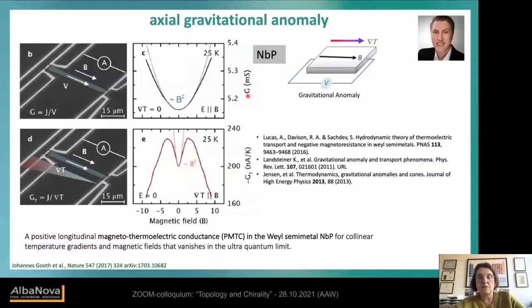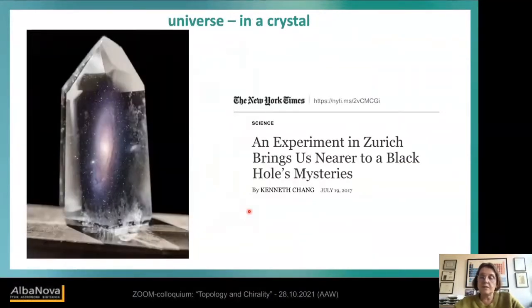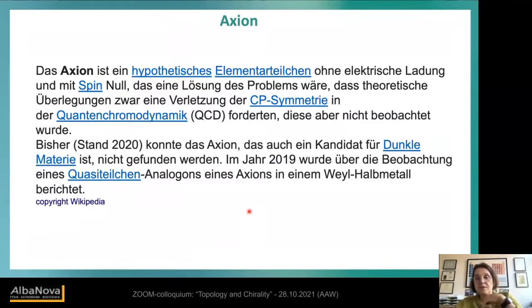Here we have the conductivity simply for comparison. So nowadays, two other materials have shown this chiral anomaly. This was gadolinium platinum bismuth, done here in our lab, and bismuth itself slightly doped with antimony, measured by Ohio State University. So this made it up to the New York Times and motivated us to look for more exotic things.